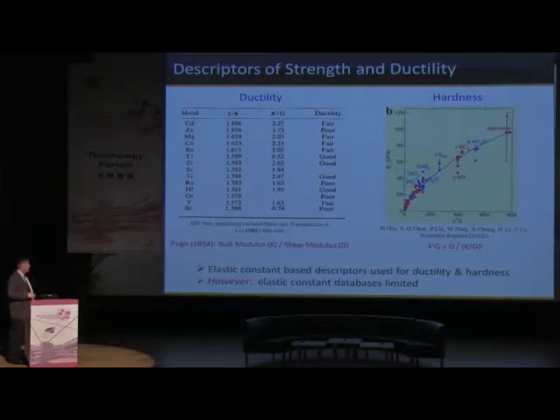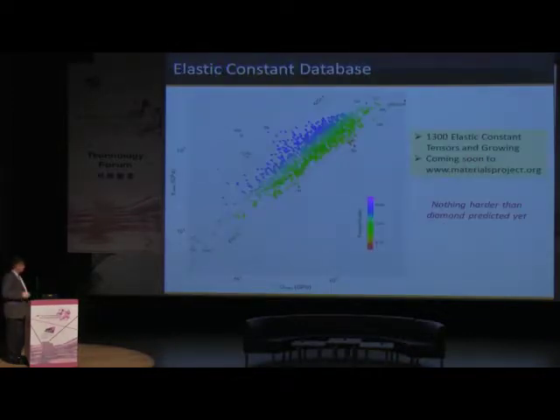We have some discriminators here, but remember I told you that the amount of materials that we know the elastic properties for is very, very limited. So if we want to screen over a very wide composition range, you have to resort to actually doing the measurements or doing the calculations. Is this something we can put into a publicly available database? Well, over about the last 2 months, we've been able to finish calculations, once the codes were written, to calculate elastic constant tensors in a fully automated way on the supercomputer.